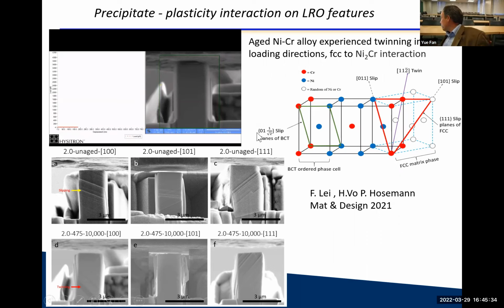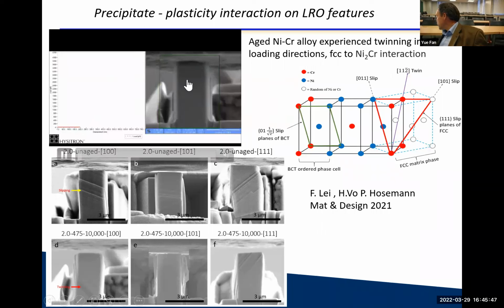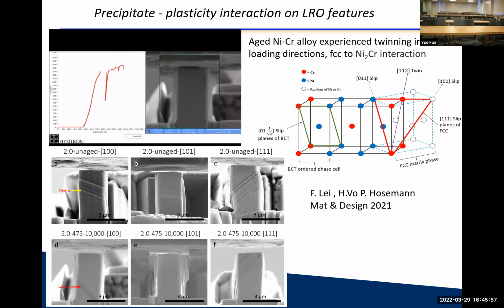So in this movie, I would like you to pay attention to a black band popping up at some point. There's a black band here popping up at some point. I don't know if you can see it or not, but it just keeps growing. So there's a first event, and then there's this dark band here, and that band keeps just widening. It's actually this band here. I think it's the same color, if I'm not mistaken. And that's not slipping, that's twinning in that instance, right? So the material actually started to twin rather than slip. But it only happened in this one orientation, interestingly. So if you do it in all the other orientations, it keeps slipping, except in the one orientation.